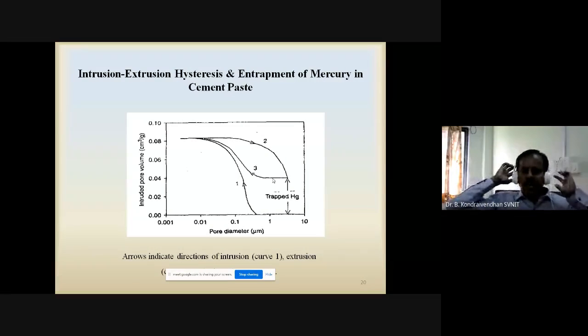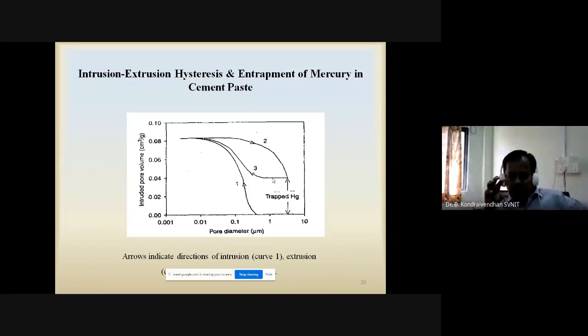So here you can see, in mercury intrusion porosimetry we are applying the mercury with high pressure. One time we apply the intrusion, and then we do the extrusion, taking the mercury back. Like that we do a number of cycles, so this kind of graph we get. Curve 1 and curve 2 are showing this. First is the intrusion, then extrusion, then intrusion again. But you can see some mercury is trapped. Why is it happening? Because it depends on the pore shapes. There are some irregularly shaped pores also. Even though the mercury at 60,000 psi can enter inside, during extrusion the whole mercury will not come out. Due to the irregular shape of the pores, we cannot take out all the mercury. Some mercury will be trapped inside the sample.